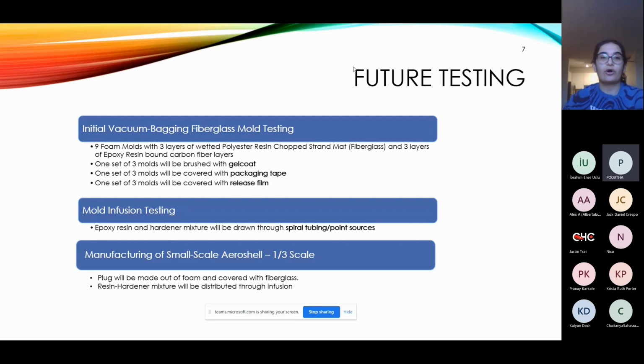There are 3 tests that we're hoping to get into. The initial vacuum bagging fiberglass mold testing, which we are doing to understand how vacuum bagging works, the properties of fiberglass and gel coat, the properties of the finished part, and to reduce supply, demand, and cost, and the use of low flashpoint chemicals. So there will be 9 foam molds with 3 layers of wetted polyester resin fiberglass and 3 layers of epoxy resin bound carbon fiber layers.